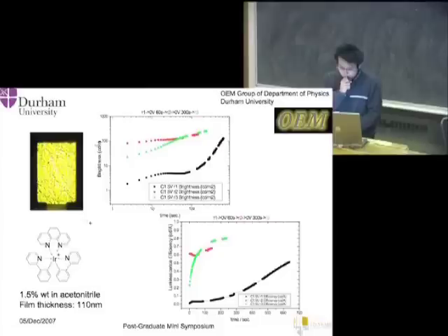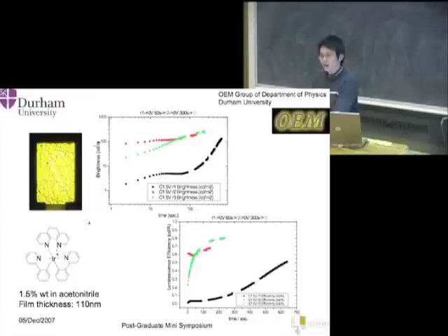So this is probably because all the anions go to the interface of the polymer and the anode. When you turn it off, the time is not enough for them to go back to the original position. So most of them are still accumulated at the interface, and when you turn it on, it still has the same effect as when you charge it.